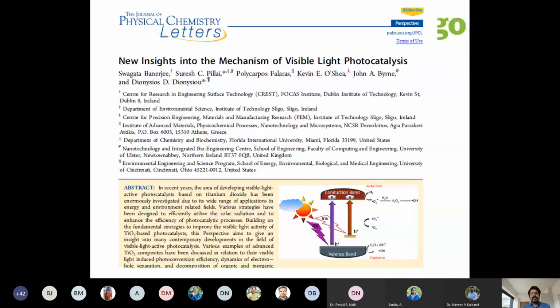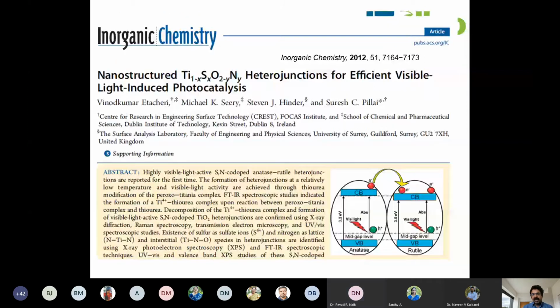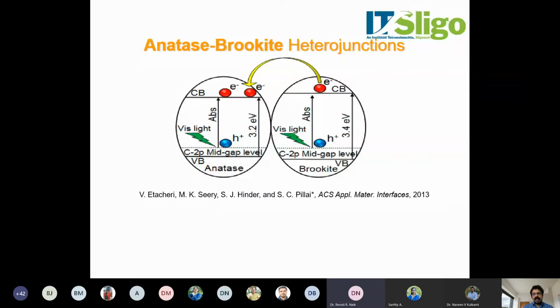And also we discussed trapping. You need to identify different types of trapping agents to improve the reaction. What happens if the electron moves from the valence band to the conduction band, the electron would come back to the valence band. We don't want that to happen. So in order to trap the electron, we can use different types of trapping agents. This is an example of a trapping agent used with rutile. In another case, we used anatase and brookite heterostructures,